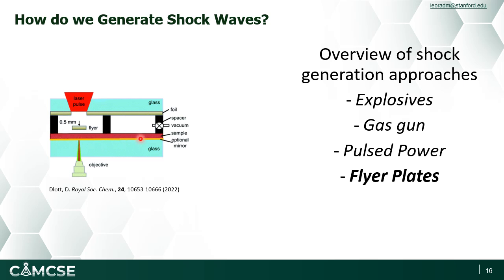The advantage to a flyer plate method like this is that, of course, you can use tabletop lasers that are commercially available to launch these types of plate compression shocks. And you can therefore have interesting types of spectroscopy or imaging that can observe the responses in a much more careful way because you have much more access to the facilities. However, there are some challenges in getting a stable shock across the flyer plates and a stable plasma within the laser pulse itself.